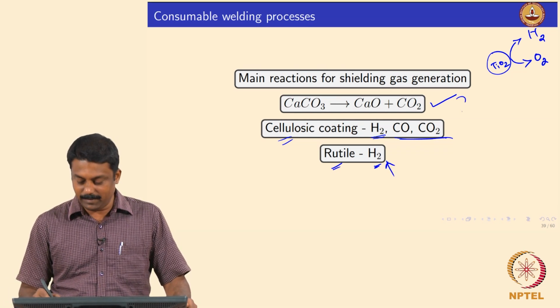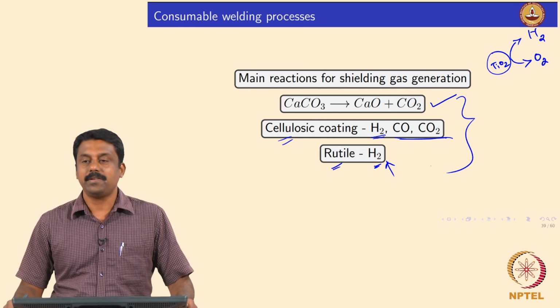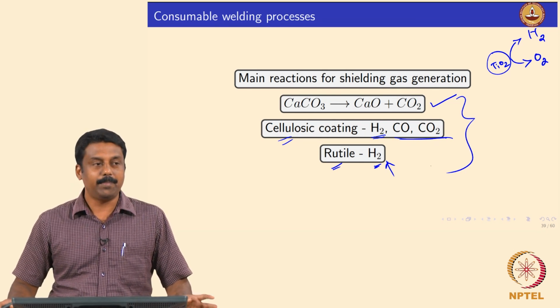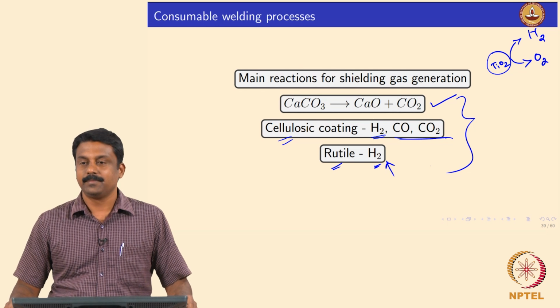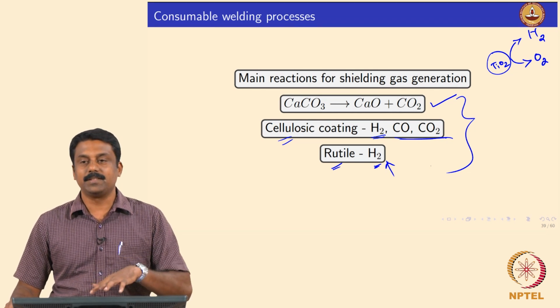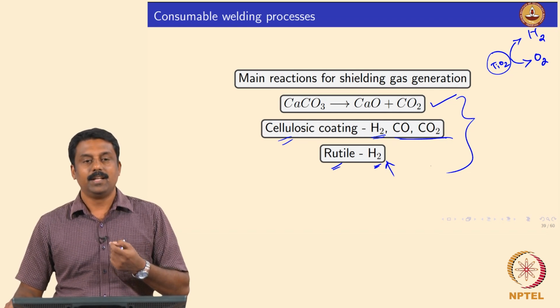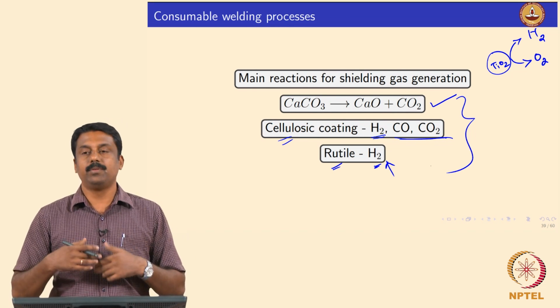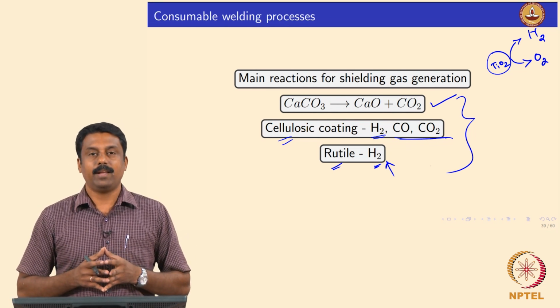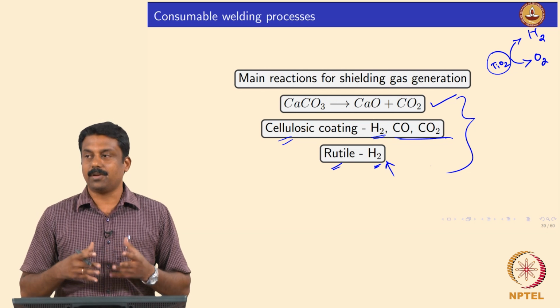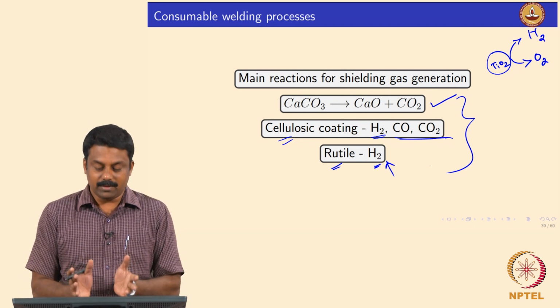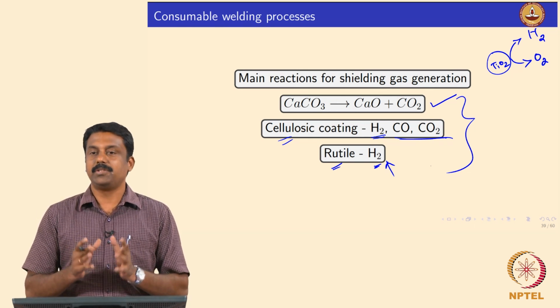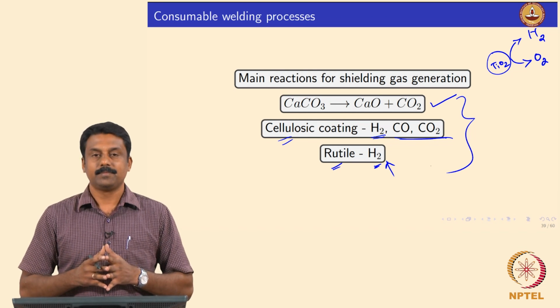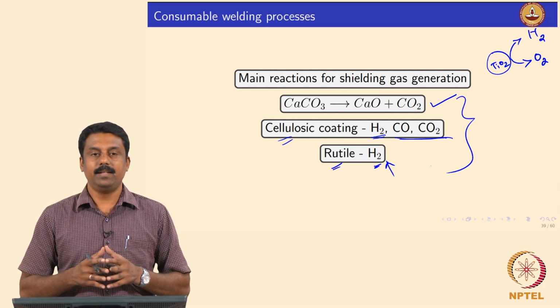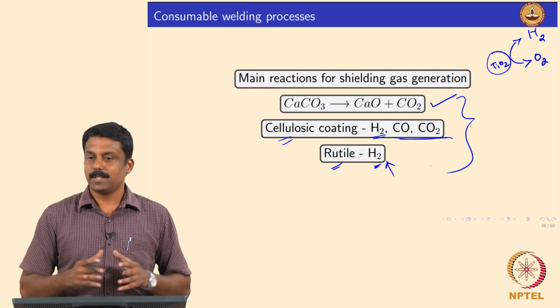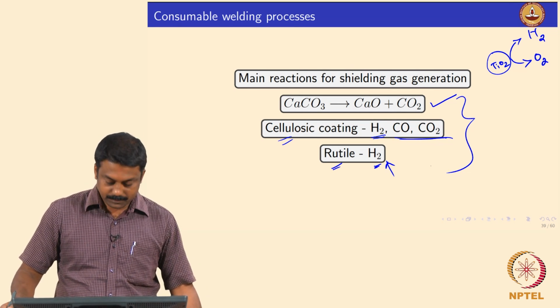So, these three are the major reactions that are happening to generate shielding gas. So, if you reduce the flux concentration, increase the metal volume fraction, then you need to use some shielding. Okay. So, in self-shielded electrodes, we do not need external shielding, because the flux decomposes and generates enough shielding gas for arcing, right. It is clear? Good. So, we move on.